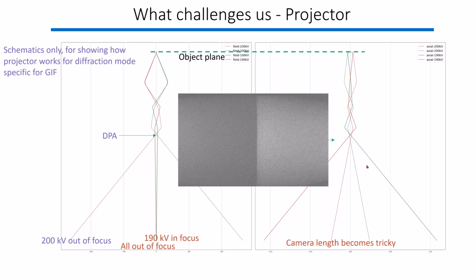And especially for this high energy loss, we do not do simultaneous dual EELS or whatever. We just acquire the data set of the zero loss first, and then go for the high loss. And especially when we're doing this resolution, which is not really up to super high resolution, which is not in any case doable, this is not really a concern for the moment, at least.